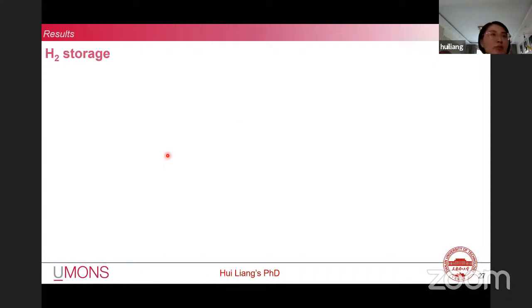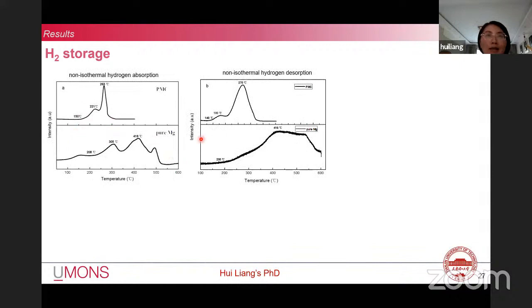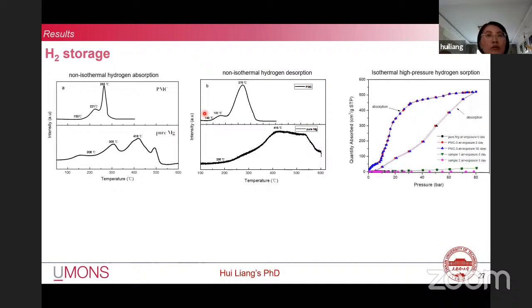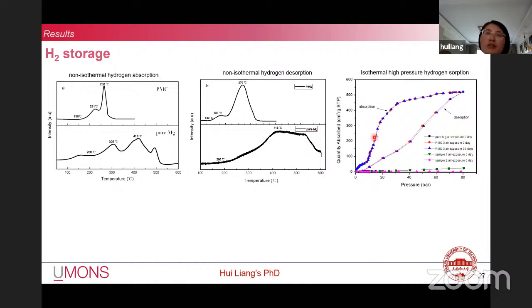For the composite H2 storage performance of PMC, refer to the non-isothermal H2 absorption-desorption curves. Compared with pure Mg, the PMC has lower absorption-desorption temperature. And the composite absorption peak is narrow, which could explain that PMC has fast absorption speed. Refer to the isothermal high-pressure H2 absorption curves. At 200 degrees, the PMC shows a faster H2 absorption within 20 bar. And when increasing the pressure to 80 bar, the H2 absorption amount is 4.25%. After 30 days in the air, the PMC still has the same H2 absorption performance as the freshly synthesized PMC.